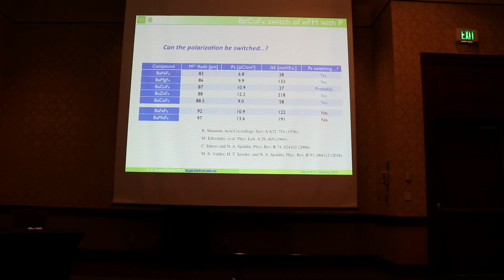So one thing that we did is try to analyze the trend through the entire family. Okay, so in here we condense the known members, synthesized experimentally, of the family, and I organize them by the radii of the B site. So for example, for the nickel case, we have 83 picometers, and in the manganese, we have 97. Okay, if we look at the polarization, it starts to increase linearly. So if we plot this, you will realize that it's a perfect line going up, and then it drops, and then it starts to go up again in the copper case. So that's exactly what we expect from a geometrical ferroelectric.